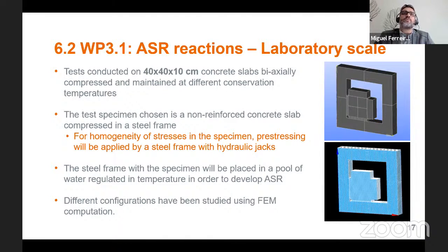So these are some of the constraints that we have, and that if you've conducted any kind of research, you understand very well. So the chosen slab was 40 by 40 by 10 centimeters, and these will be biaxially compressed and maintained at different conservation temperatures. So the specimens are not reinforced, and they are compressed by a steel frame, and you can see that in the image, the finite element modeling that was done. And the stress will be applied by hydraulic jacks, and then these frames at the same time will be placed in a pool of water in the case of ASR, or in different temperature and humidity conditions in the case of creep and shrinkage.